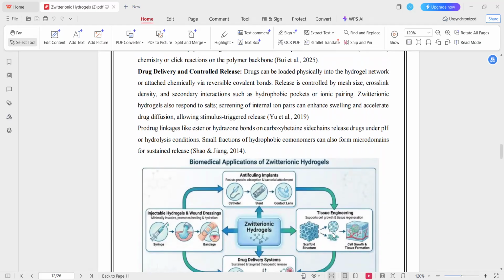Drug release is also influenced by the interactions inside the gel. Some drugs stick to the polymers through ionic interactions while others sit inside small hydrophobic pockets. Zwitterionic hydrogels can respond to changes in salt concentrations. When salt screens the internal charges, the gel swells, the pore opens, and the drug diffuses out faster. This makes controlled or stimulus triggered release possible.